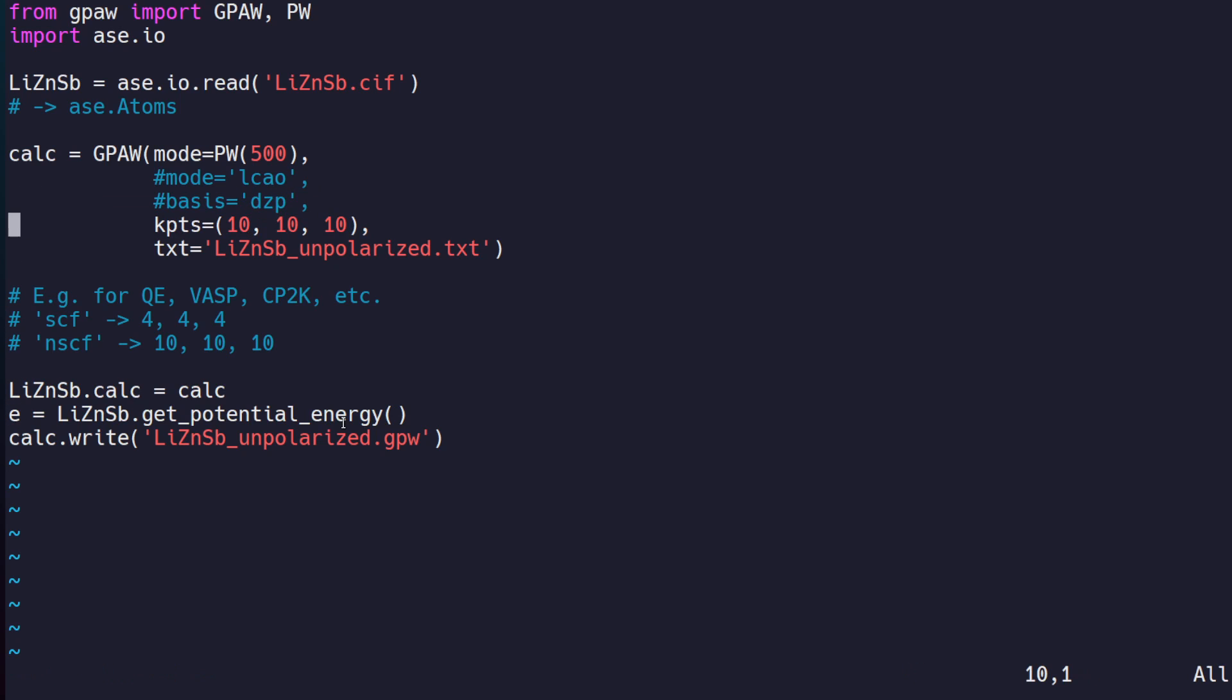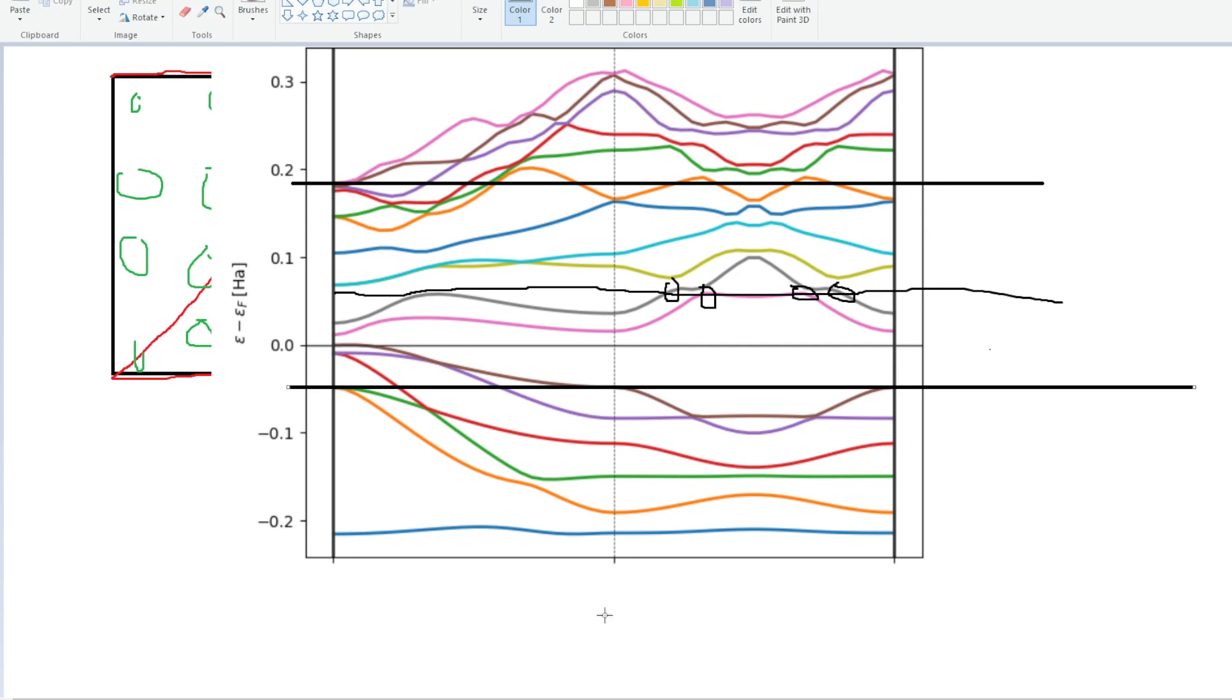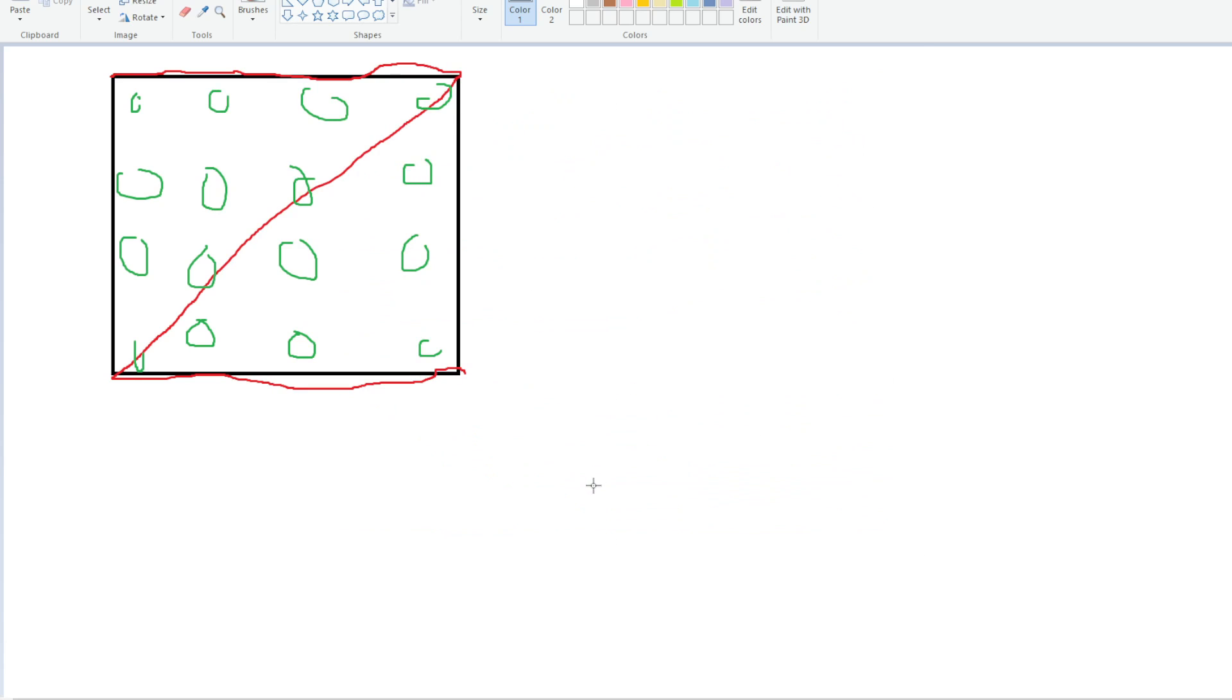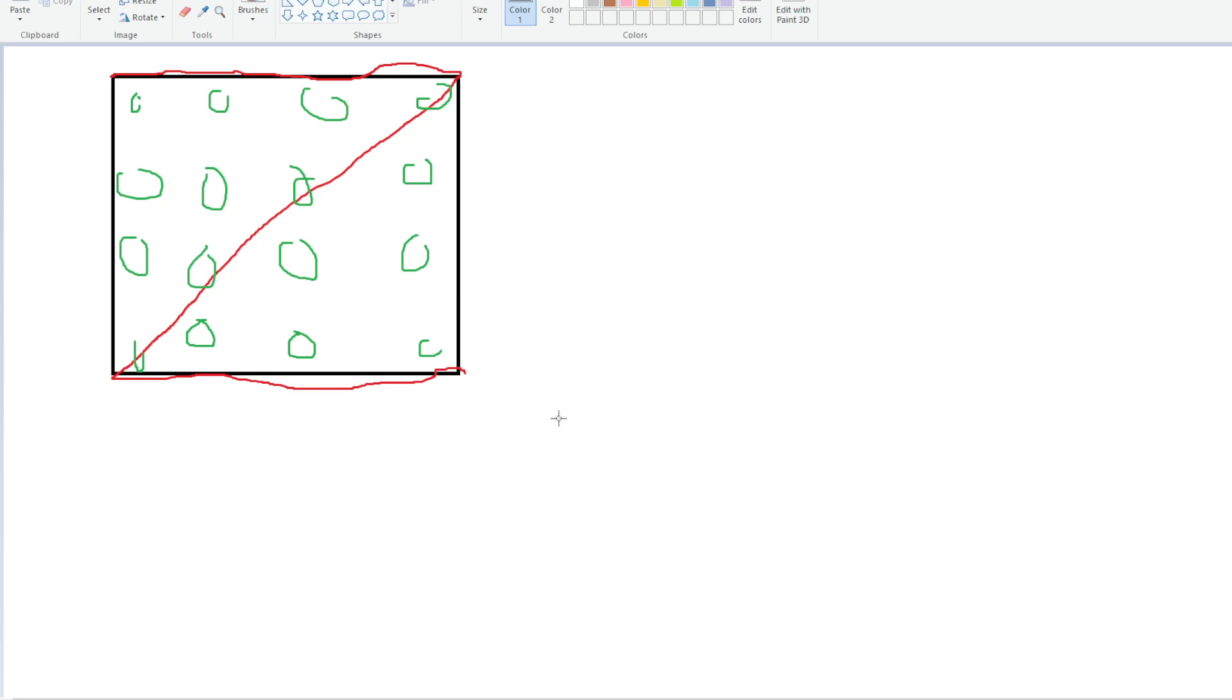If you're dealing with a bigger system, one thing to keep in mind: always use a unit cell, never use a non-unit cell for a BoltzTraP2 calculation. The goal is to interpolate the energies at a given k-point representative of the unit cell. So two things: always use the unit cell and always use a uniform k-mesh. Do not pass a band structure calculation to BoltzTraP2.